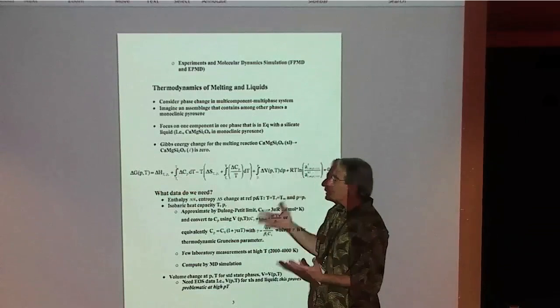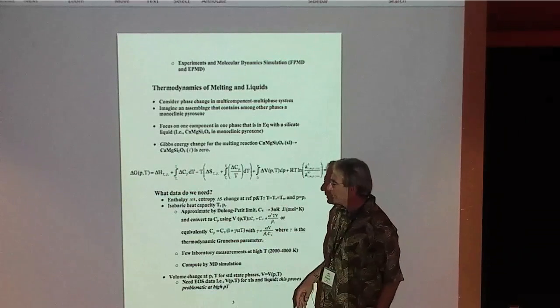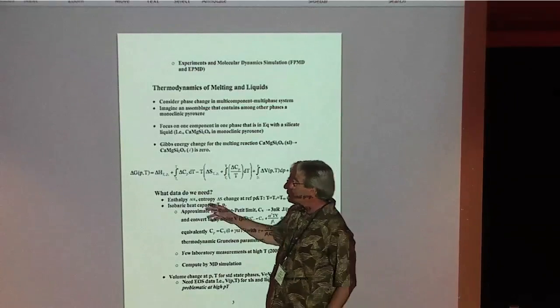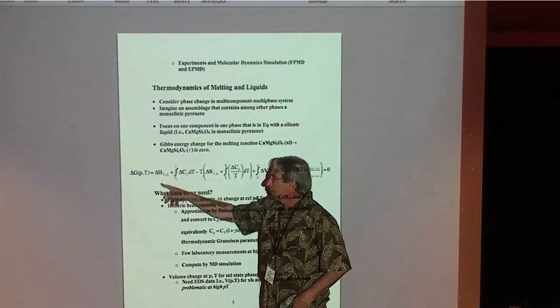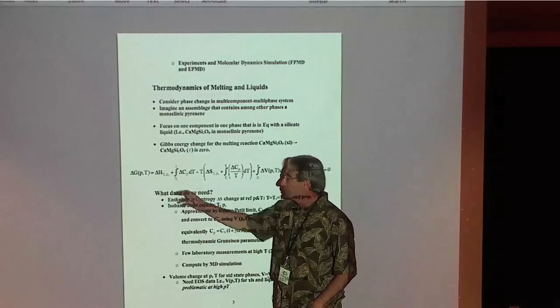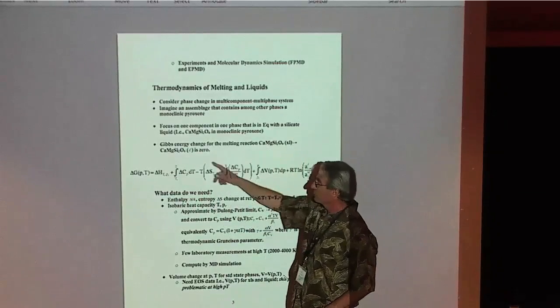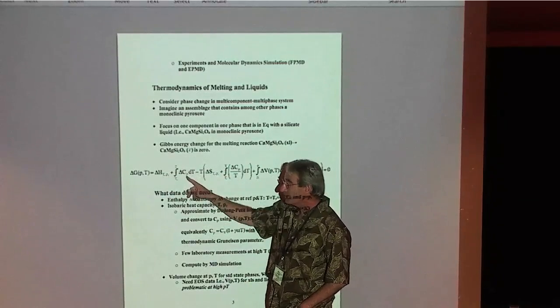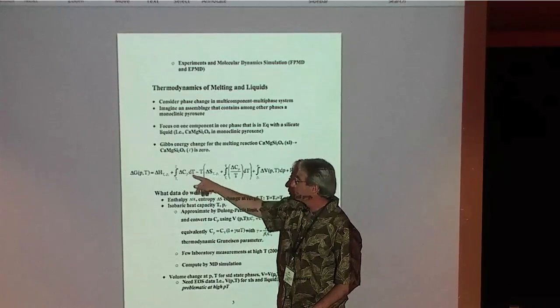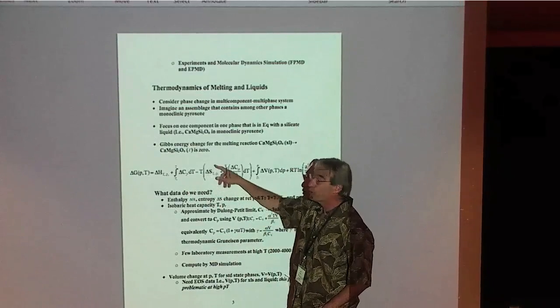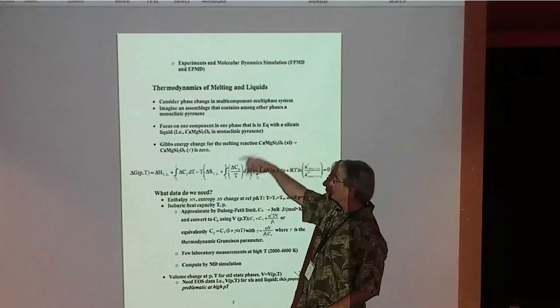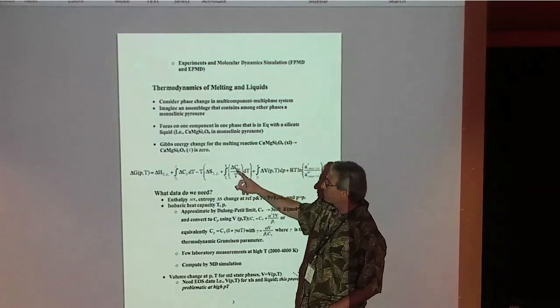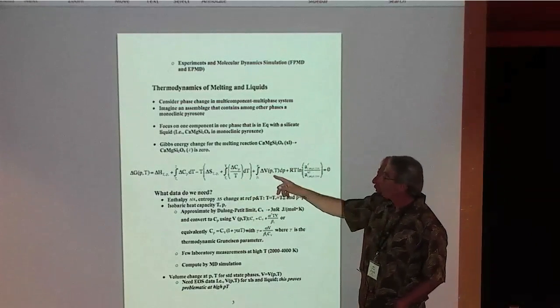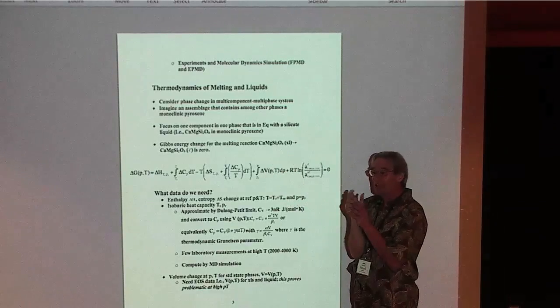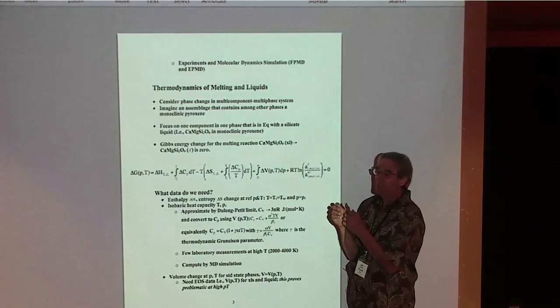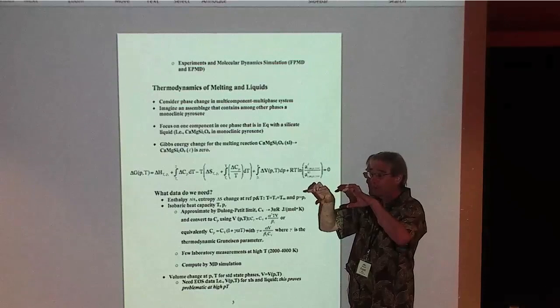How does that depend on pressure and temperature? Well, here it is in all its ugly or beautiful glory. It depends on things like the enthalpy of formation of the material, the enthalpy of the reaction, the enthalpy of fusion, heat capacity, an integral there, the entropy difference between the liquid and the solid, the heat capacity difference between liquid and solid, and an integral over the delta V of this reaction, the change in volume, essentially the change in density of solid crystals versus liquid.